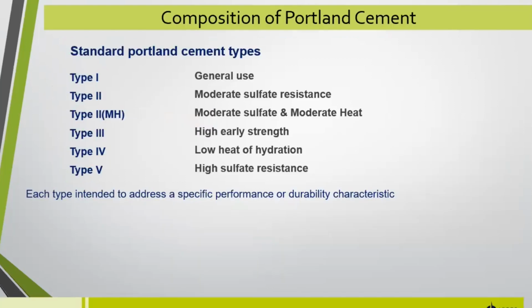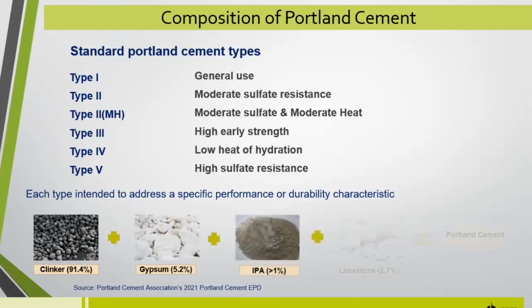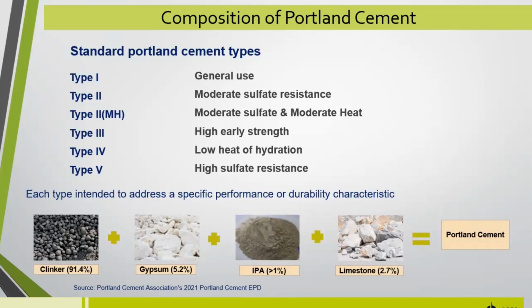So when you're talking about ASTM C150, the composition of Portland cement, again, we've got types 1 through 5 here. And as you can see, each of those types has very specific performance or durability characteristics associated with it. And I want to look briefly at the composition of Portland cement. So the numbers you're looking at here are actually an industry average. These come from the PCA's EPD on Portland cement. And as you can see, we've got roughly 91% clinker, a little over 5% gypsum, some process addition, and then 2.7% limestone. This is in Portland cement, and again, these are industry averages.